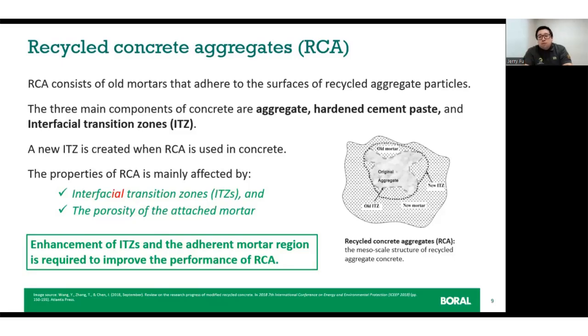Unfortunately, we can't just simply swap out the natural aggregates for recycled concrete aggregates. There are some significant differences and drawbacks regarding recycled concrete aggregates. After crushing the recycled concrete down to different aggregate sizes, the process can introduce microcracks within the residual mortar and weaken the bond between the original aggregate and the old mortar.